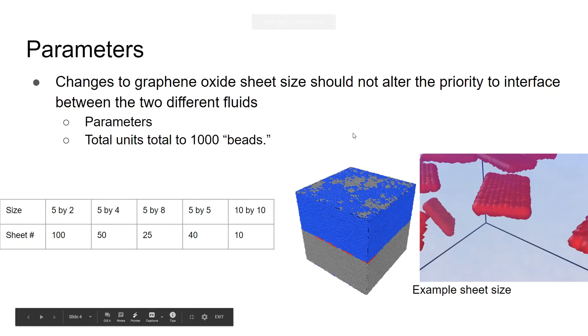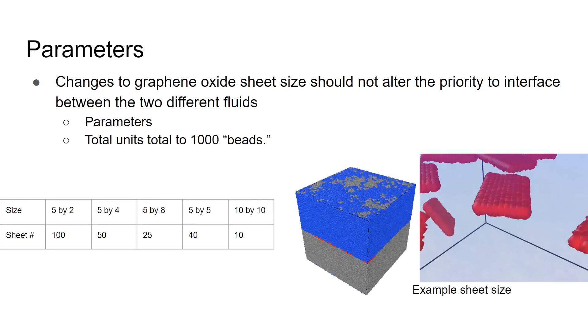For this project, we defined our parameters such that we would always be investigating the sheet size effects on the graphene oxide. We predicted that graphene oxide sheet size would not alter the preference to interface between the two different fluids. There are three different bead types: blue beads, gray beads, and red beads. The blue and gray are two arbitrary solution beads, and the red beads are the graphene oxide beads. We defined a total of 1,000 beads, so a 5x2 sheet means 10 beads per sheet with 100 sheets, giving 1,000 beads total. Similarly, a 10x10 sheet uses only 10 sheets, keeping total bead count constant so concentration stays the same while only sheet size changes. A 10x10 sheet literally means 10 beads across and 10 beads wide.